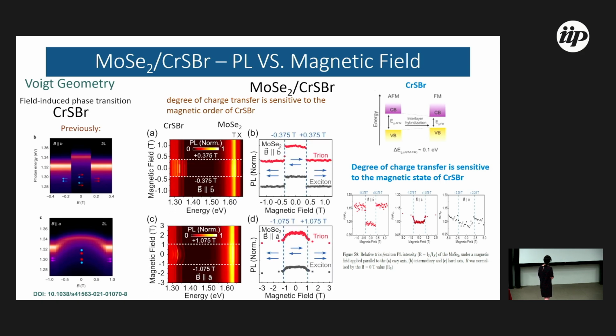Another thing that happens: this was previously published about CRSBR, that the exciton is a probe of the phase. When I measure MoSe2 on CrSBr, what we see is that the intensity of MoSe2 is correlated to the phase transition. So the exciton intensity is probing the phase transition of CrSBr. And why? This is how it changed. When I have a spin flip, I have an abrupt change in the PL intensity. When I have a spin canting, I have a smooth change of the PL intensity. It happens because the band gap change of CrSBr changes with the phase.